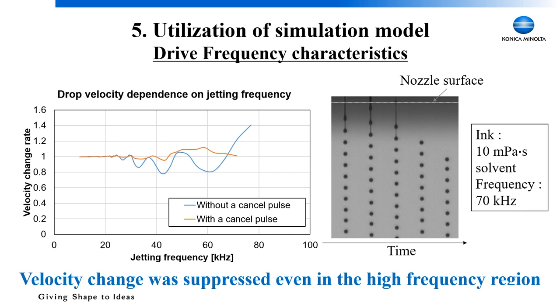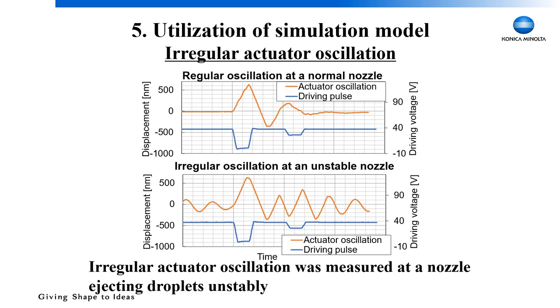And the actuator oscillation also gives information about the inside of the ink channel. We observed irregular actuator oscillation at the nozzle ejecting droplets unstably. This graph shows the regular oscillation and irregular oscillation. The applied driving pulse was the same. In this graph, the irregular actuator oscillation shows a higher frequency than the regular oscillation. We analyzed why this phenomenon occurred.